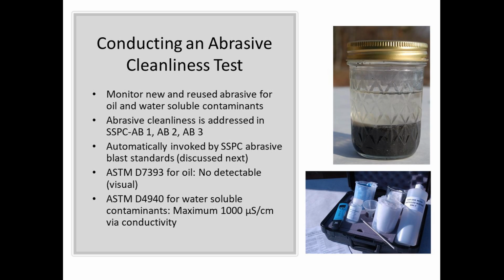So we're not supposed to have any visible oil on the top surface of the water. We are allowed to have some conductivity to the abrasive. So the maximum amount of conductivity is 1,000. For below 1,000, SSPC says that abrasive is considered clean. If it's over 1,000, we have an issue.